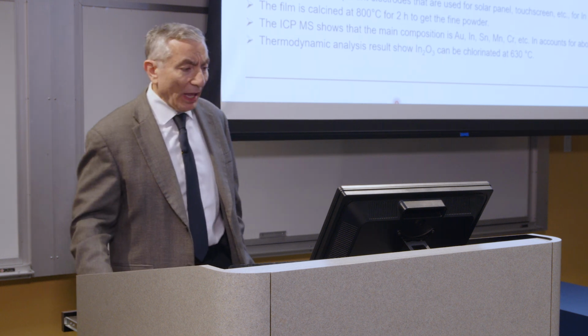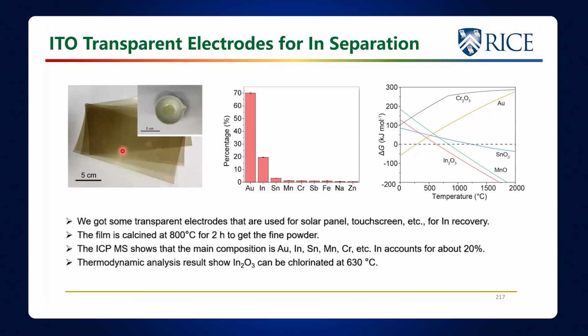So we got some plastic that has indium tin oxide on it, and we just calcined this, which means you just heat it up in air. That burns away all the plastic and leaves just the metals. So the metals just end up in here. And there's actually more gold in here than there is indium, so we'll go after the gold as well. So it's gold and indium, and then a lot less of tin, manganese, chromium, and antimony, and you just go through and get lower and lower amounts of elements.